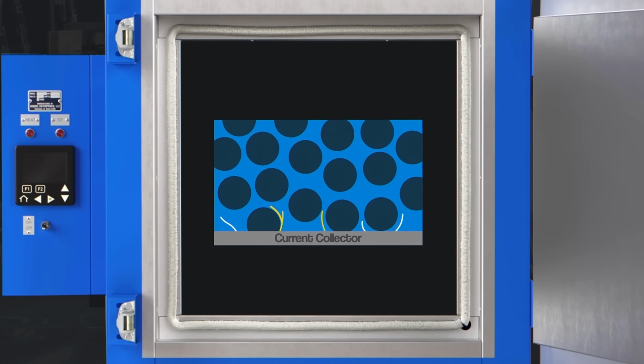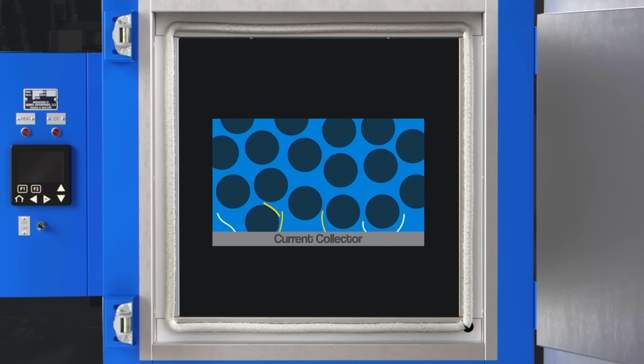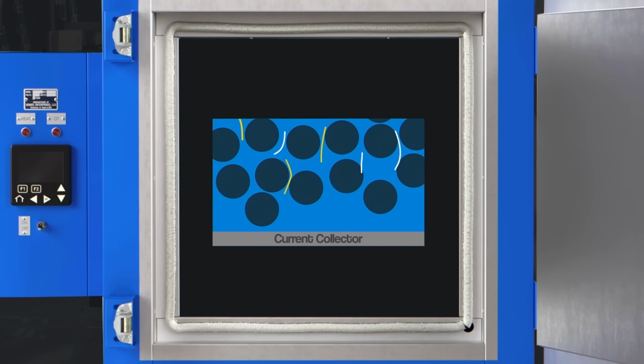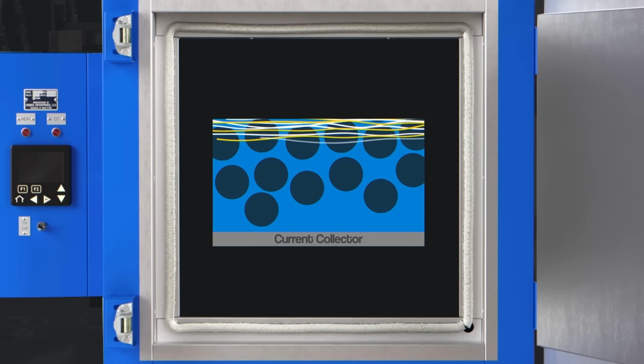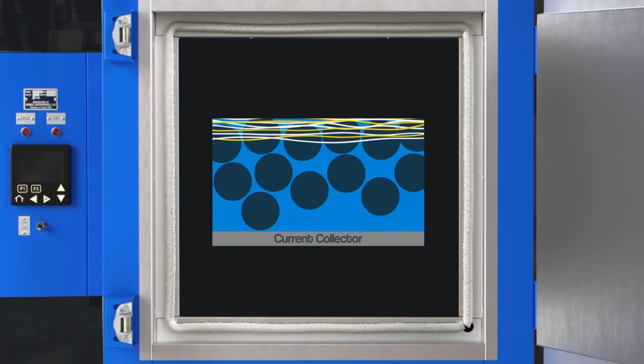When a wet slurry is dried in an oven, the evaporating solvent carries the binder towards the surface of the electrode, taking binder away from the bottom of the electrode layer. This creates weak spots near the current collector, which limit how thick you can make the electrode, and ultimately caps the energy density you can achieve, because thicker cathodes store more energy. With the dry electrode process, there's none of that binder migration, so there's enough binder throughout that it stays strong and you can have much thicker cathodes, and therefore more energy dense batteries.